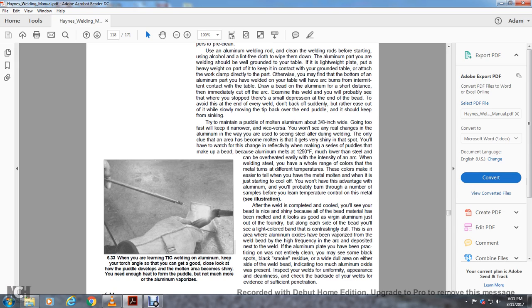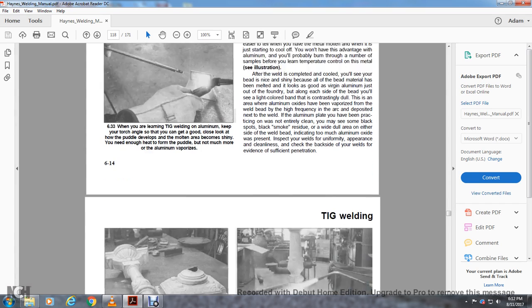But along the outside of the bead, you'll see a light-colored band with a contrasting dull finish. In this area, the aluminum oxide has been vaporized from the welded bead by the high frequency in the arc. If the aluminum plate you have been practicing on was not entirely clean, you may see some black smoke residue with a wide dull area on either side of the welded bead, indicating that too much aluminum oxide was present. When inspecting your welds, look for uniformity, appearance and cleanliness, and check the back side of your weld for evidence of sufficient penetration.